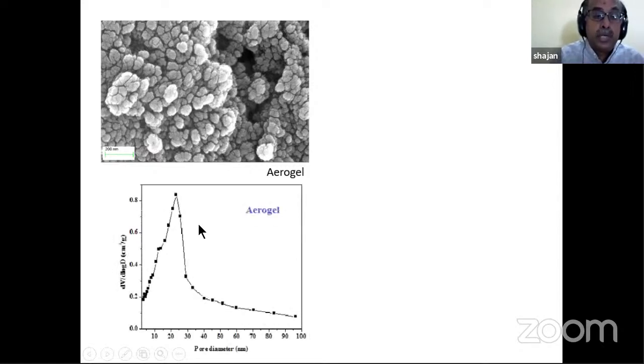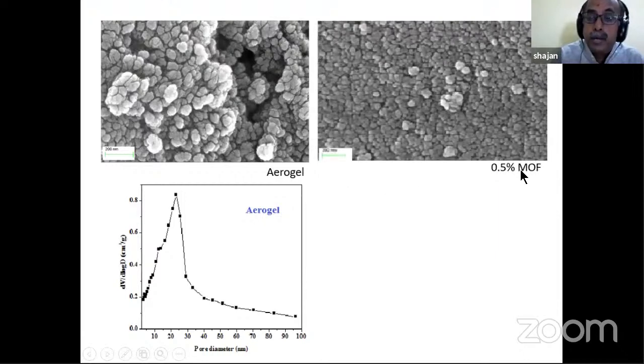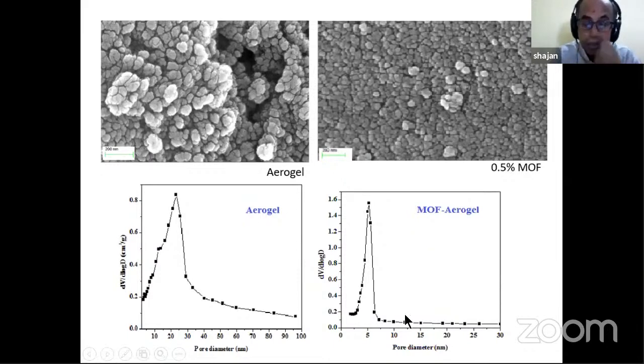Using the BET surface analysis, you can calculate the pore diameter. It ranges from around 8 nanometers to 30 nanometers. Now to this aerogel we mixed the MOF, say 0.5% nickel BTC, and you can see the difference. The pores become uniformly distributed and reduced in size. You can check here: almost all the pores are distributed around 5 nanometers.